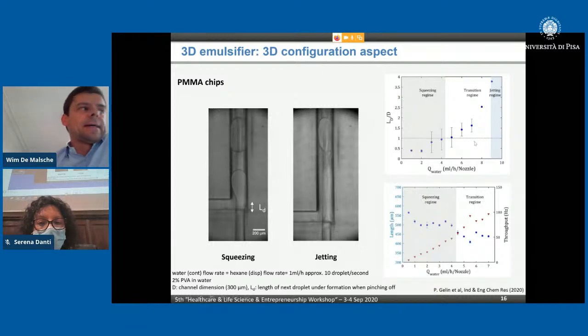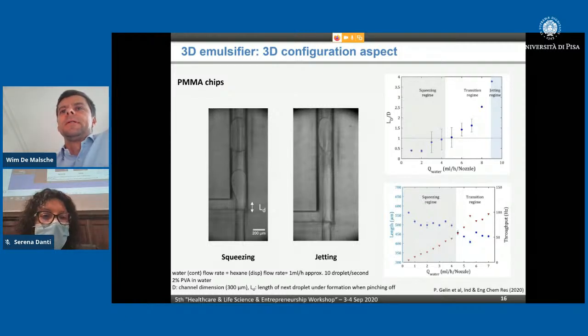And pressure is in fact not really limiting for us. We typically only work below 5 bar. So for all the work we're doing, 5 bar is enough, but we could go to 100 bar if needed. Even for chromatography applications, we apply up to 400 bar on our chips. So in general, pressure limitations are not very relevant, but what is a limitation is that you don't want to go into crazy unstable regimes.